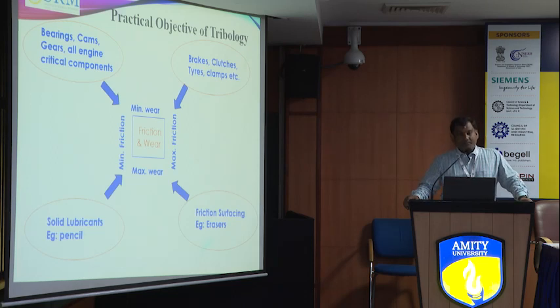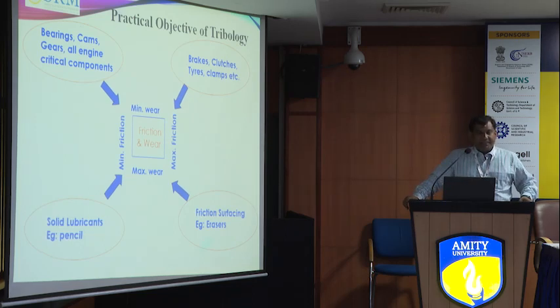There we require minimum wear and minimum friction. Then we can develop some coatings, either thermal spray coatings or polymer coatings, to reduce the friction and increase the life. And sometimes we require maximum friction and minimum wear. That maximum is not that much; it is the optimum friction, but it should be at least 0.4 to 0.5 in that range. Like brakes, we require friction, and only then can your vehicle stop. But we require that the brakes will not burn out fast and can last longer.